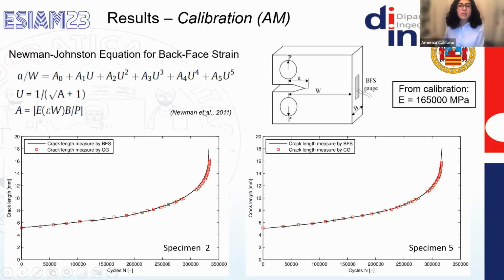The data collected using the back face strain gauge and the crack gauges were compared and calibrated using the Newman-Johnston compliance equation for back face strain, as my colleague Dr. Giannella already showed in his presentation. So using these equations, it is possible to calibrate the measures and to compute the Young modulus for the considered material. And from calibration, it was found that the Young modulus is 165,000 megapascals for the additively manufactured stainless steel.